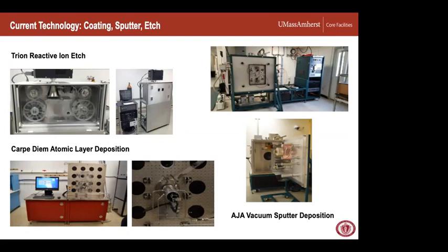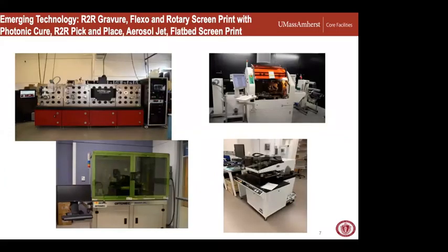So you don't need real high temperatures, and you can do those on even some of the plastic substrates that are out there. Additional emerging capability, as mentioned in the top right, we have this coating capability with the photonic cure system in the middle, the PulseForge, you can see that. Basically that's a UV flash lamp, which just hits the substrate with these intense UV pulses that heats up the films that have been patterned and coated on that, and then cures and densifies those, basically sintering them.